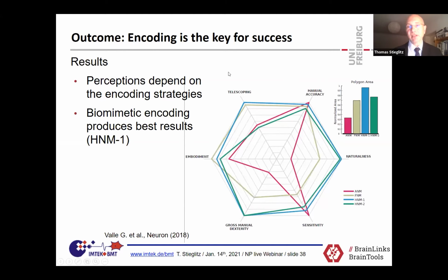Encoding is the key for success. If you have just fixed frequency, fixed amplitude pulses, you can get something. But if you play around with changing pulse to pulse distances and adapting the pulse shape over the stimulation train, then you also get telescoping and better embodiment. That means that people feel their hand moving from the stump site, where they feel it before getting that prosthesis, to the original site where it was before amputation, and they feel the limb really as part of their own and can increase manual accuracy and sensitivity.